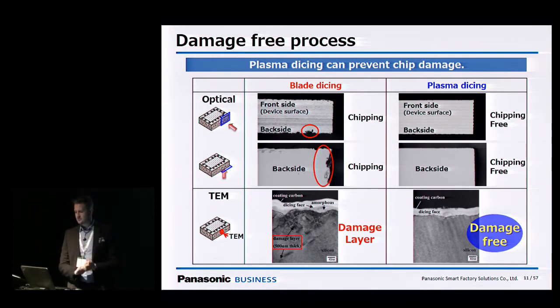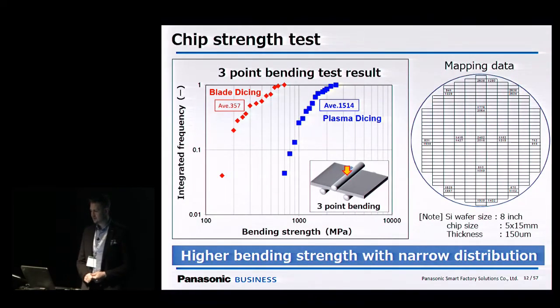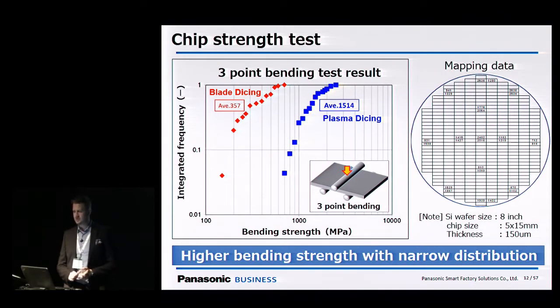So again, if we look at the damage caused by blade dicing on the left, you can see the chipping and the damage-free evidence on the right from plasma dicing. But why is this really important? Well, if you take the chips and perform a bending test on them, you can see that plasma diced chips in blue are much stronger.